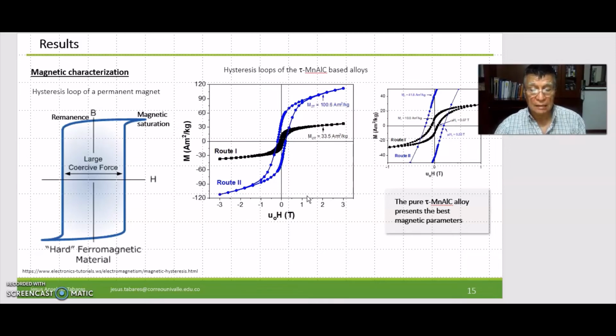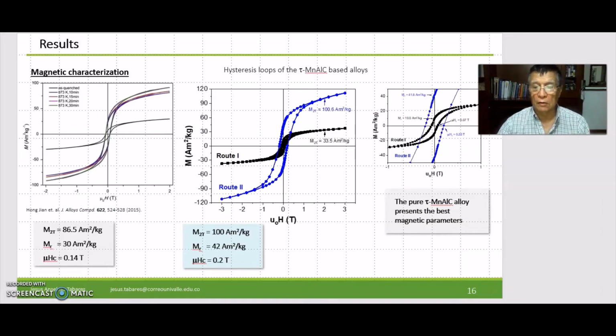The pure one has magnetization at the external field of 2 Tesla of around 100 ampere square meter per kilogram, a remanence magnetization of around 42 ampere square meter per kilogram, and a coercive field of 0.2 Tesla. The pure tau manganese aluminum alloy presents the best magnetic parameters. Comparing these results with those obtained by Hongjin, we found that our tau manganese aluminum carbon has optimized magnetic parameters that are relevant to design high-performance rare earth free permanent magnets.